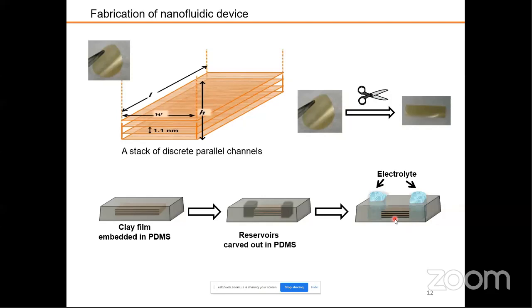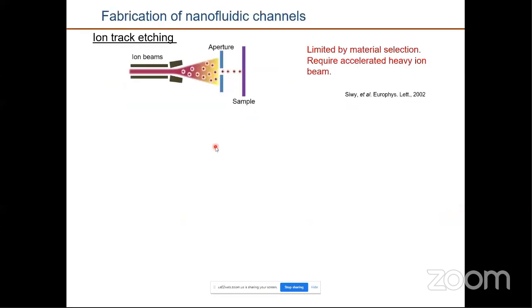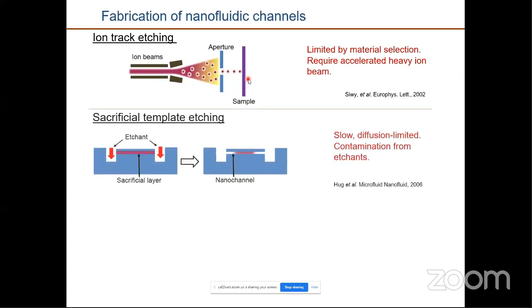Before going to the actual results, I just want to show how such channels are usually made. For example, one technique to make these small channels to study properties of material under confined space is ion track etching. This is not what we do actually. Normally people use this technique to make nanofluidic channels. We generate very high energy ion beams and pass the beam through the material in which we want to make the channels. Then we use a chemical etchant to etch away the ion track so that we get a small hole in it. And then we can study the ion transport through this.